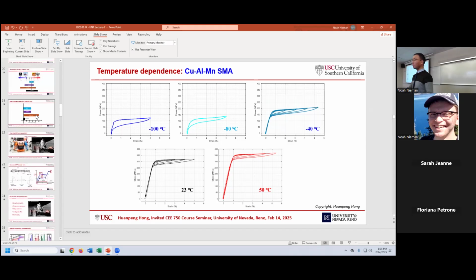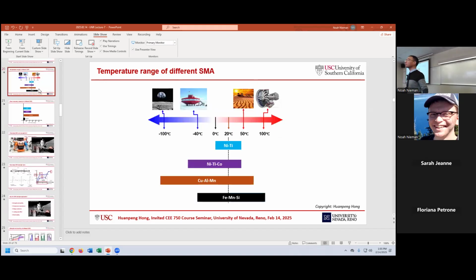I see. So the one that was put in the bridge was -10 degrees Celsius, meaning that up to -10, it is superelastic. Going lower than that, it will have some residual effects. And AF is something that they control during manufacturing. Exactly, it is intrinsic. So we need to test them with the same AF from the manufacturer. If the AFs are significantly different, like 0 and -40, you cannot compare the temperature.